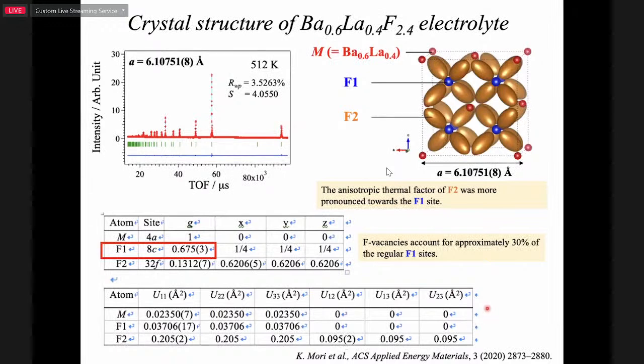Okay, let me show you the result of the crystal structure analysis for barium lanthanum fluoride. This is the neutron diffraction data. The red mark indicates the observed data, the light blue solid line indicates the calculated data, and the blue solid line is the difference between observed and calculated data. As you can see, we could obtain an excellent fit like this, and finally refine the crystal structure, with anisotropic thermal factors.